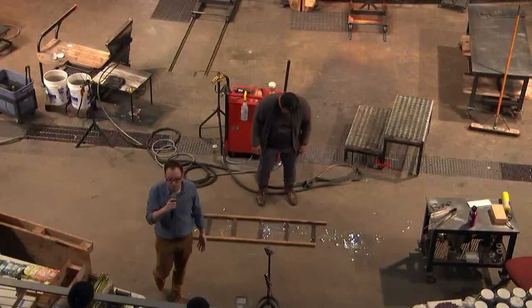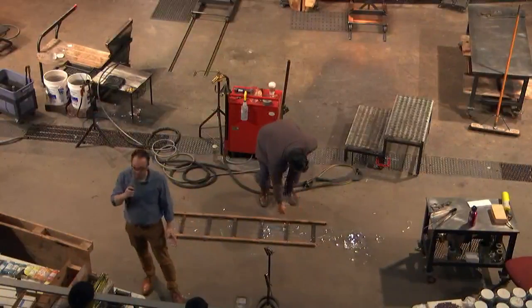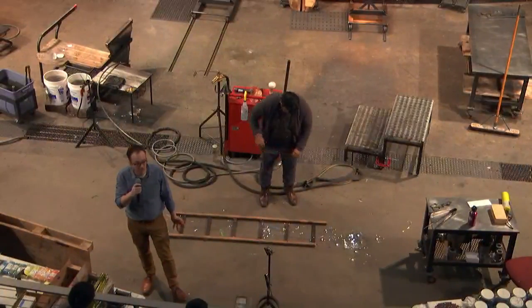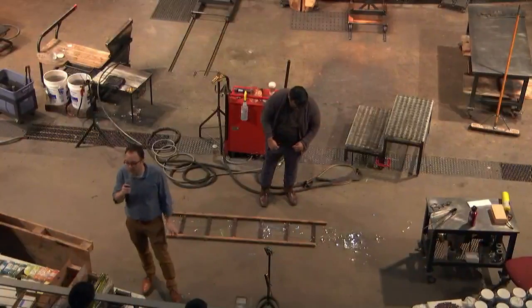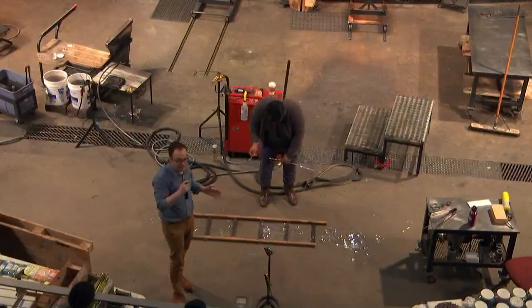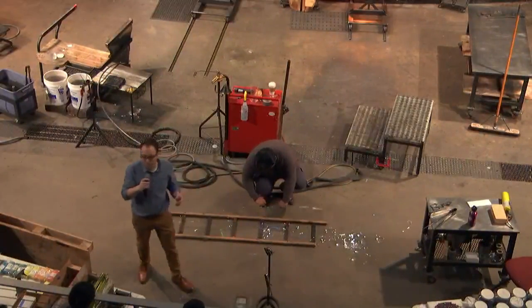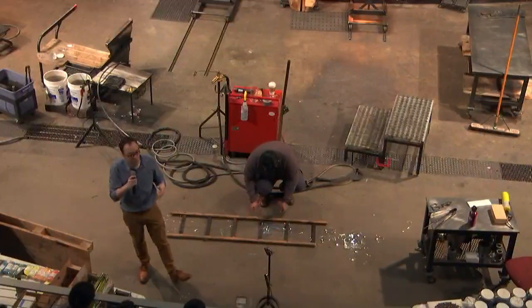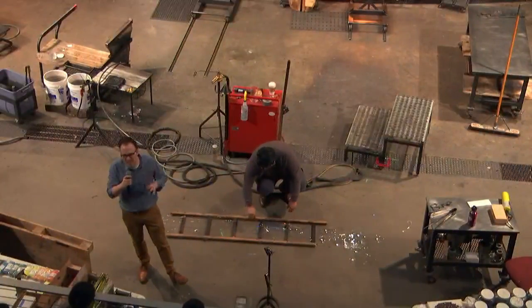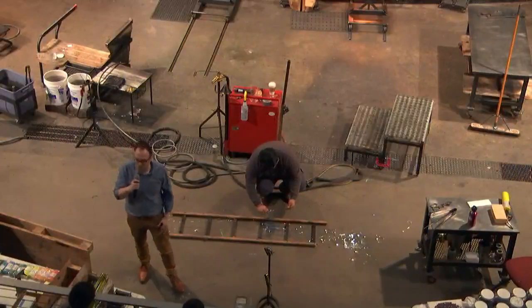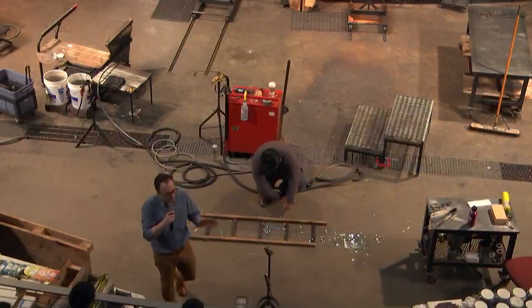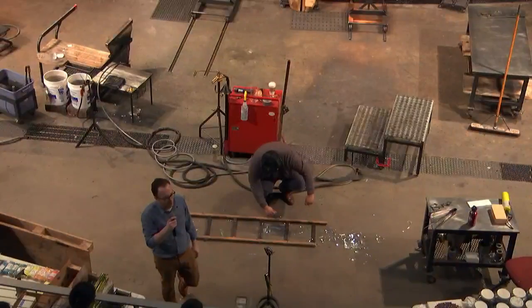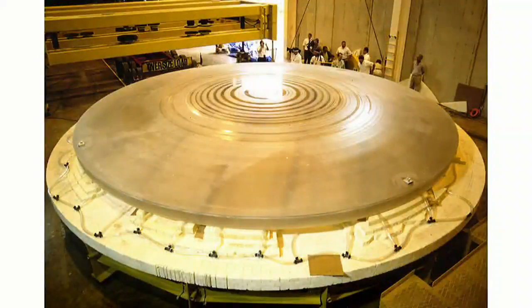For larger works of art, especially for cast glass, that can take up to 10 to 12 days here. Some of the really big pieces of cast glass, including mirrors for telescopes. The largest piece of glass that's ever been made was a mirror for a very large telescope. It took 3 years for that glass to cool down. And they do that in order so there's no breaks, no cracks, nothing going on inside the glass. All right, there's a picture of that giant mirror, actually. Pretty cool, right? So glass has lots of really amazing applications.